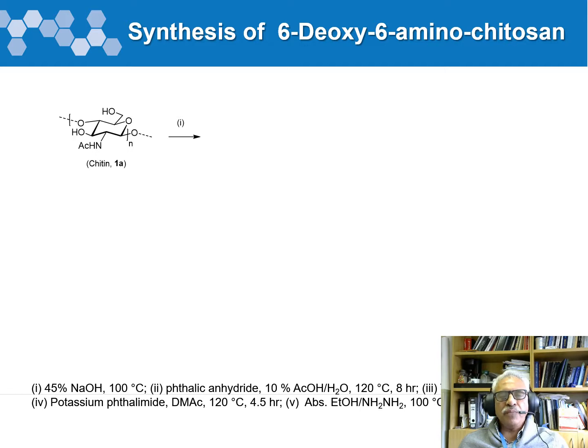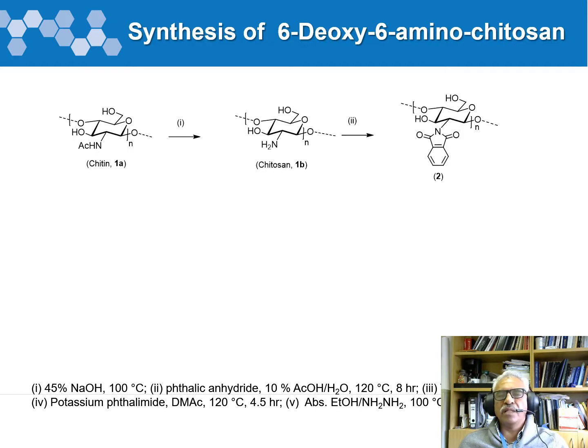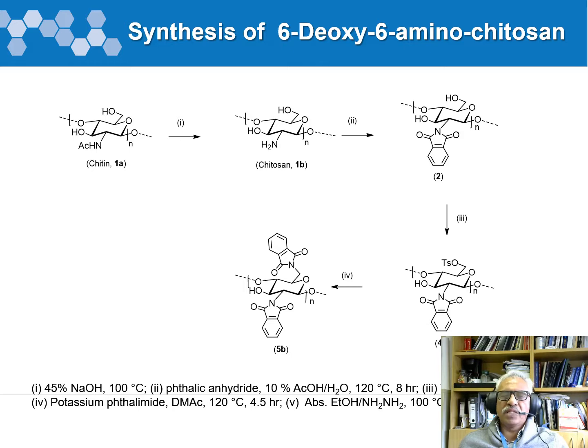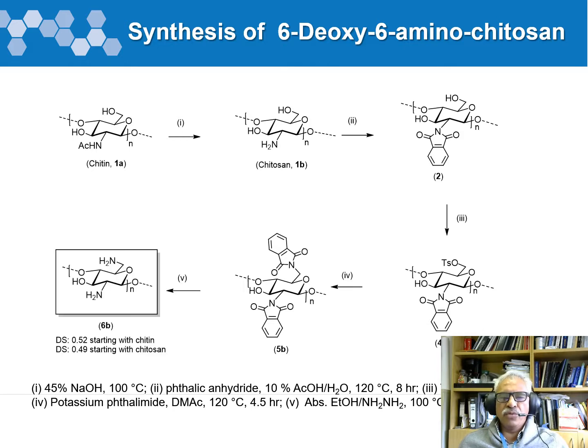Now we have a process whereby we can take chitin, convert it to chitosan, protect the amino group, tosylate that, and then we switched here from using sodium azide, we use potassium phthalimide as a nucleophile. And potassium phthalimide then substitutes this tosyl group, and all we then have to do is a global deprotection like we've done before to remove the phthaloyl groups to give us the diamino chitosan. Now this product gave much better yields, and also we did not have to deal with the problem of triphenylphosphine getting stuck in the polymer. So the solubilities were much greater for our product than that which has been reported.